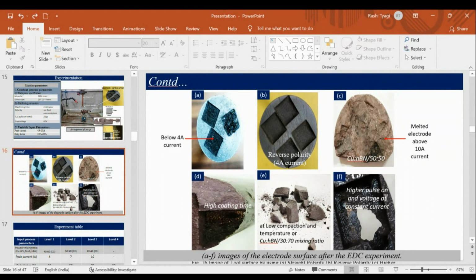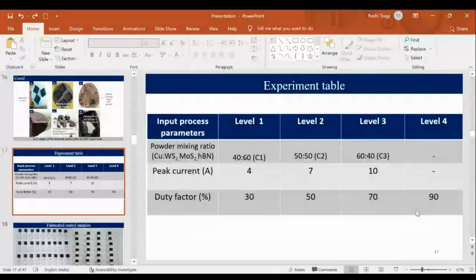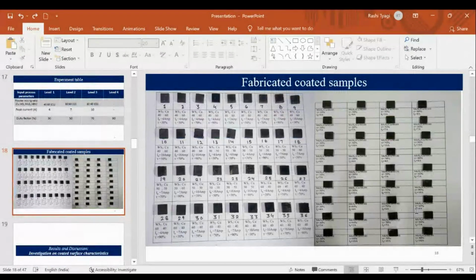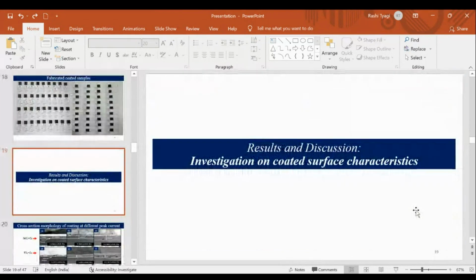This is the higher pulse on time and higher voltage time. So we have fixed a constant pulse on time and voltage to deposit the coating. So there's the experimental table on which we have performed these experiments using solid lubricant. There's the fabricated coated sample that we have obtained after performing the EDC experiment.